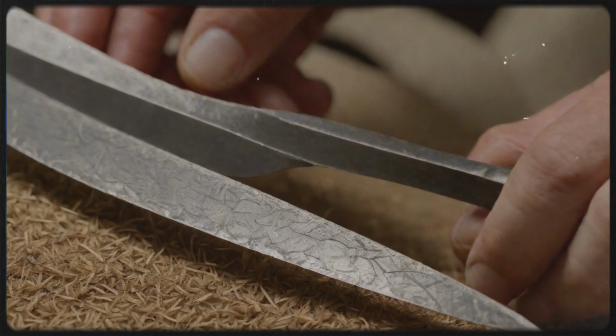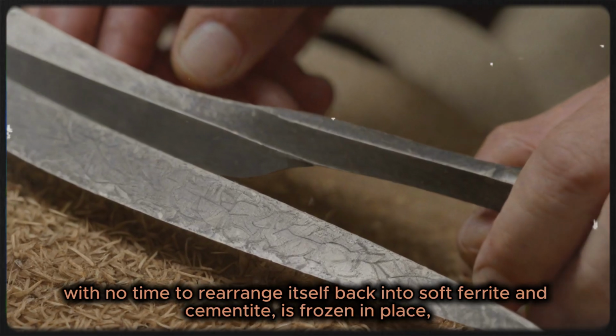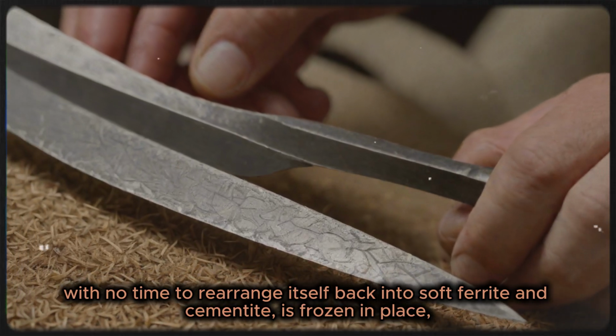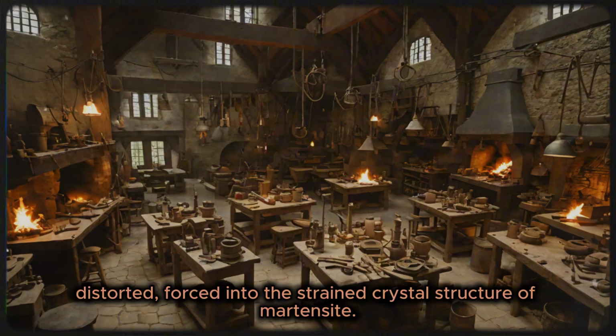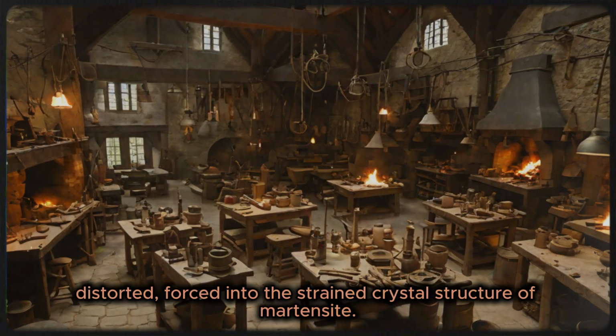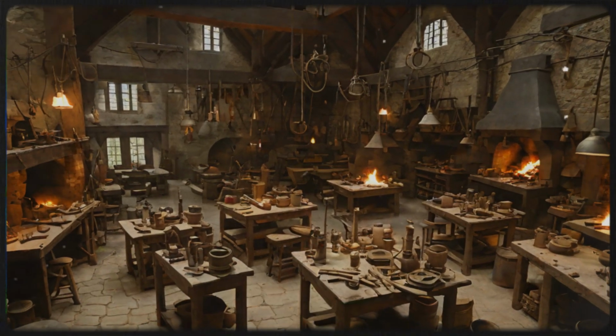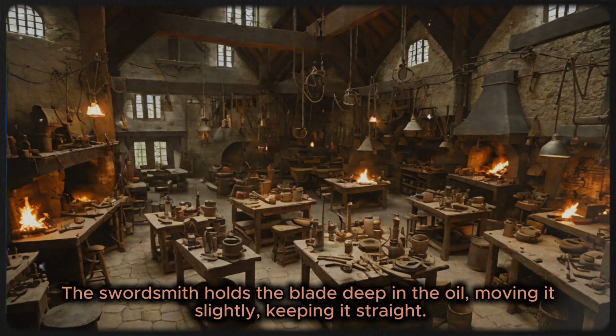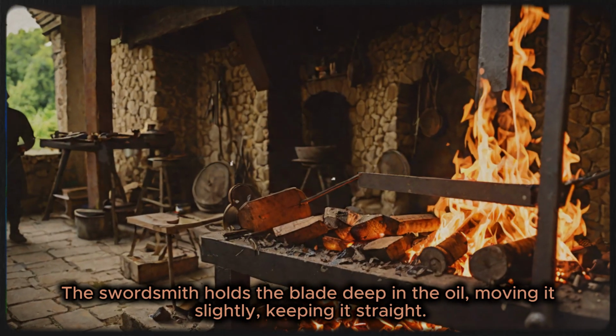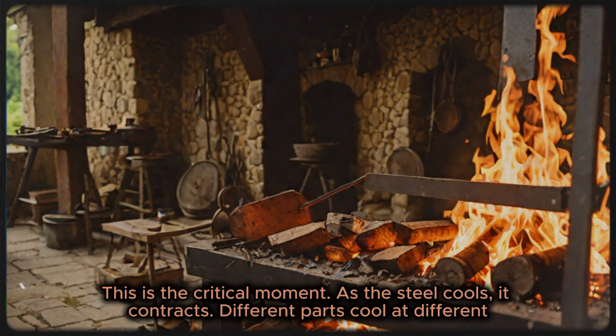The austenite, with no time to rearrange itself back into soft ferrite and cementite, is frozen in place, distorted, forced into the strained crystal structure of martensite. The swordsmith holds the blade deep in the oil, moving it slightly, keeping it straight. This is the critical moment.